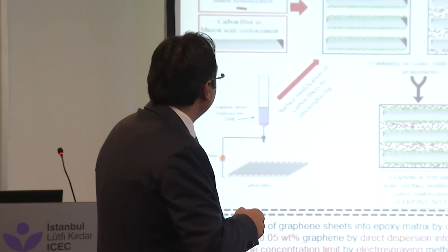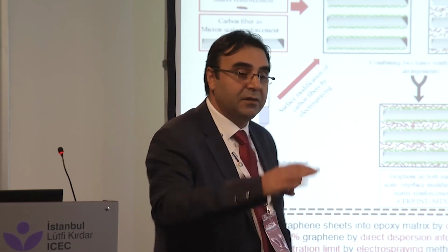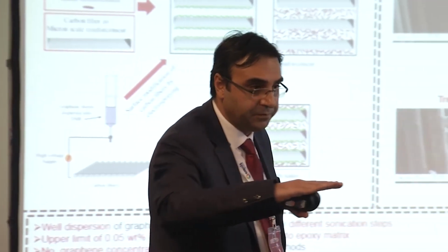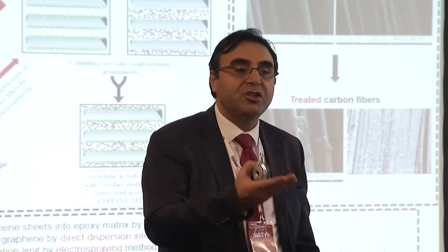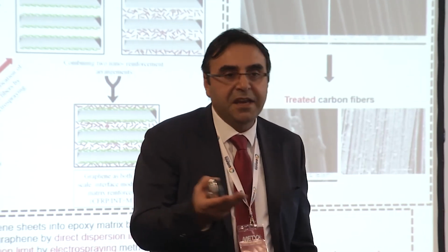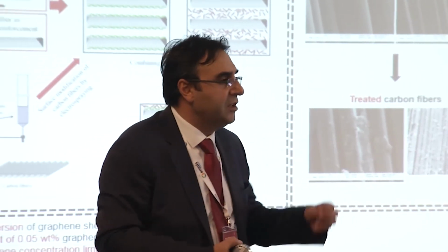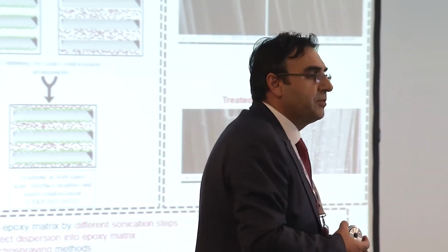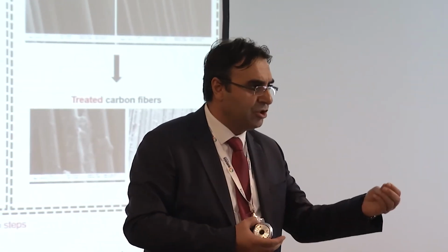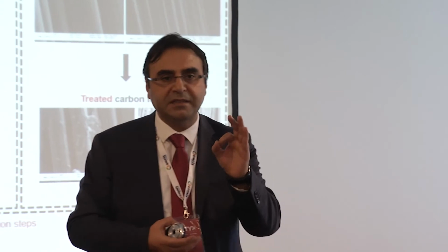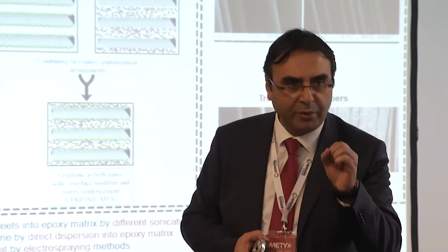So we said that we will incorporate this first onto the textile. We create a suspension of the graphene, and there are different methodologies. Either you can spray it onto the surface with an airbrush, but then you will have a very big droplet size, so that you will have agglomeration.